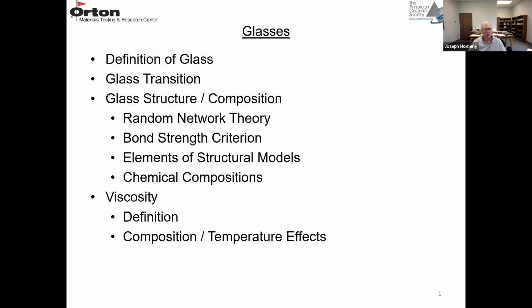So we'll go over the definition of glass, definition of glass transition, and we'll look at some glass structure composition relationships. There's a random network theory, a bond strength theory. There's certain structural elements that are in these models, and then we'll look at chemical compositions, primarily silicate glasses, which are what is present in refractories. And then we'll look at viscosity, define viscosity, and look at how the composition of the glass affects the viscosity. A viscous glass at high temperatures is not as serious as a glass that's fluid, because that will really lower the high temperature performance of a refractory.